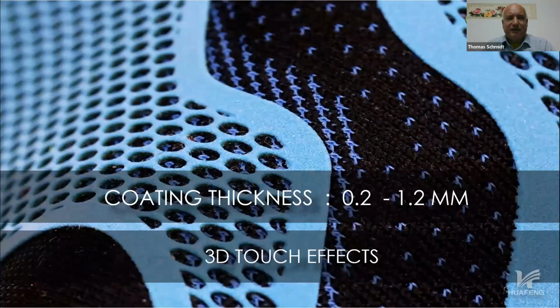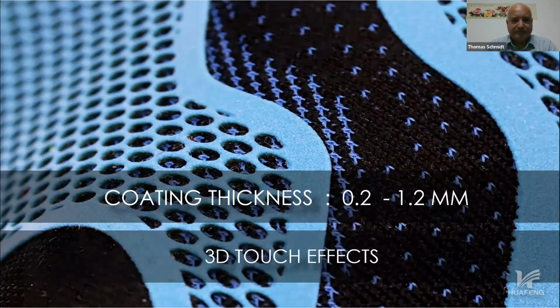And the coating thickness for shoes, usually we use between 0.2 and 1.2 millimeter coating thickness. And just because of the coating thickness, we can also achieve a special touch performance. So in addition to the touch of the textiles, we can add 3D coatings, which you can very clearly feel when you touch the material.